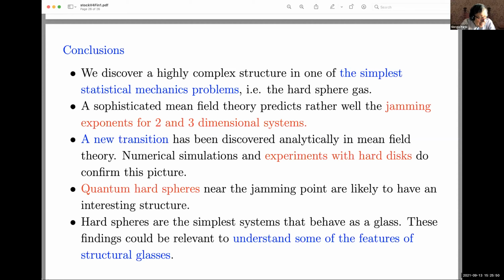Now, the fact that mean field theory holds up to 4 dimensions is something which depends on the type of system. If you are doing the computation, for example, in the case of percolation, the upper critical dimension requires not a 4 minus epsilon expansion, but a 6 minus epsilon expansion. Therefore, mean field theory breaks down in 6 dimensions. If you go to the tricritical point, or to some special point for the liquids, not a critical one, but the end point of the liquid-gas phase transition, the critical exponent works up to dimension 3. And therefore, you have a 3 minus epsilon expansion.